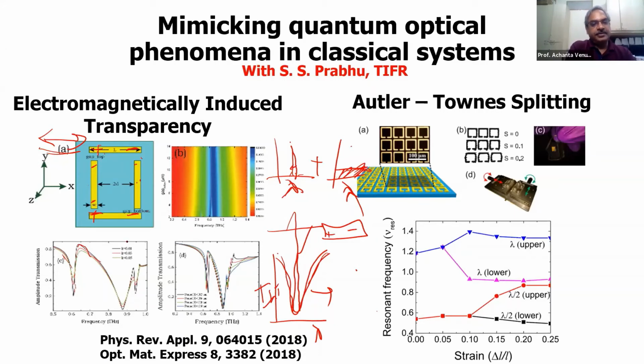So then you'll have two Fano resonances, and these two Fano resonances can also interact. And what you see is one is a very broad resonance compared to the other one, which is really sharp, right? So you can get high Q resonances using these Fano kind of line profiles, interaction between, say, for example, dipoles and quadrupoles. Right? So in the weak coupling regime, we see the so-called electromagnetically induced transparency. So within this dipolar dip, you see a transmission enhancement.